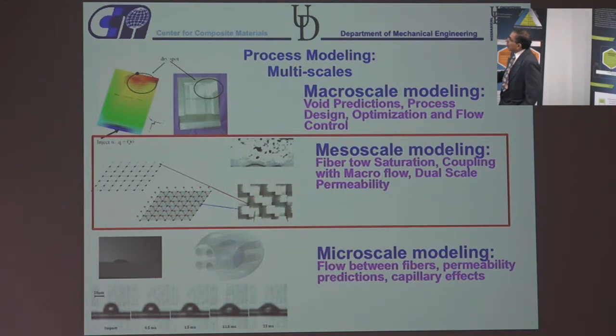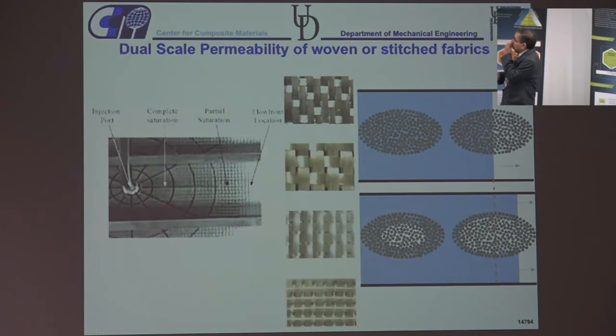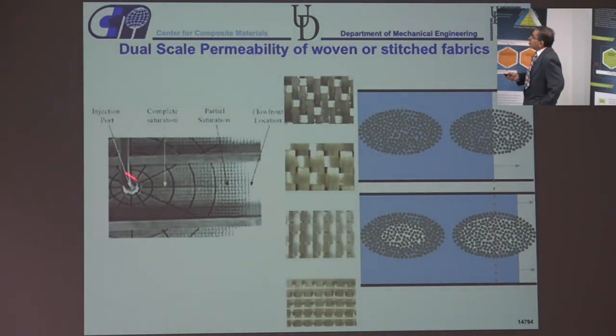So we decided to say, okay, how do we address that? Here we did some experiments where you inject the resin, and notice how it's all dark here, but you have some white areas. The reason is the toes are still filling. So the resin is coming in, and initially we were modeling it like this: the toes are filling at the same time as around the regions, but in reality what's happening is the resin is going further and these toes are filling later on. And if you don't fill those toes, that's your porosity, right?